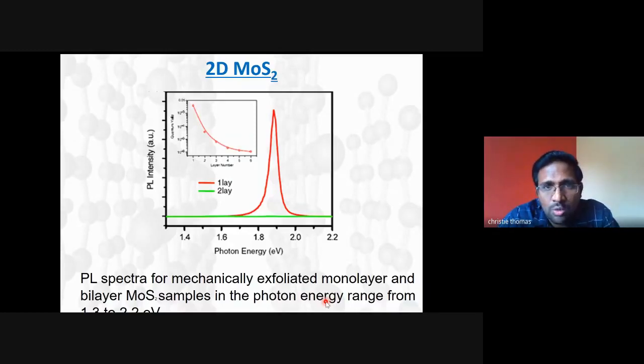As you all may know, the bulk MoS2 crystal is an indirect semiconductor with a band gap in the range of 1.2 to 1.3 electron volt. Okay, bulk MoS2 is an indirect band gap semiconductor. You know what is meant by indirect and direct band gap semiconductor. For indirect band gap material, the band gap luminescence will be a weak phonon assisted process. Okay, there will be a lot of loss, phonon loss. So the quantum yield will be very less.